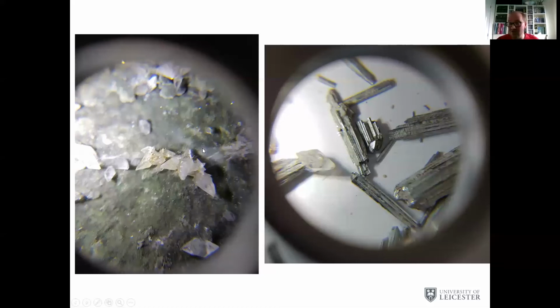And tellurides are usually not very spectacular. In fact, most of the time we need an SEM to see them. Some of the background here is a little bit sparkly. It's a mixture of calcite, and there are some tellurides there. Sometimes the tellurides are absolutely beautiful. Sadly, this is a sample that remained on the bookshelf of the geologist that found it, and he wouldn't give it to me, though I think I deserve it.